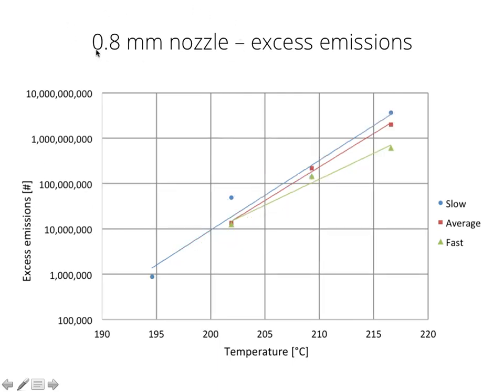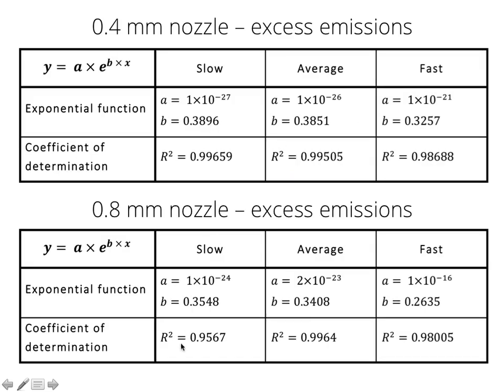It actually got worse for the 0.8 millimeter nozzle. We had quite extreme excess emissions at the beginning. It was a lot worse for the 0.8 millimeter nozzle than for the 0.4, so there are literally particle emission bursts at the beginning. Again, this has to do with overheating the filament and the heater block having an inhomogeneous heat distribution at the beginning. We can again explain the increases exponentially, but the fits are, as you can see here, okay-ish.